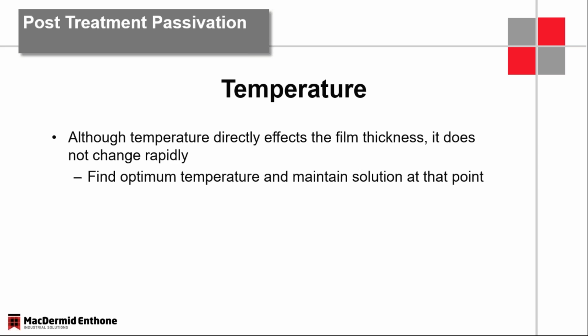If you try to passivate something at 65 degrees, 70 degrees, it might not take at all. Zinc nickel is a very good example of that. Zinc nickel is a very hard deposit. It needs that extra temperature to help bite through the deposit. So the idea is to find your proper temperature for your situation and keep it there.